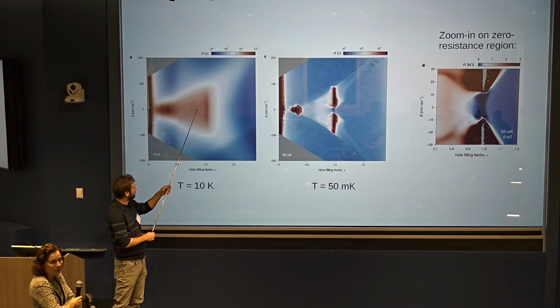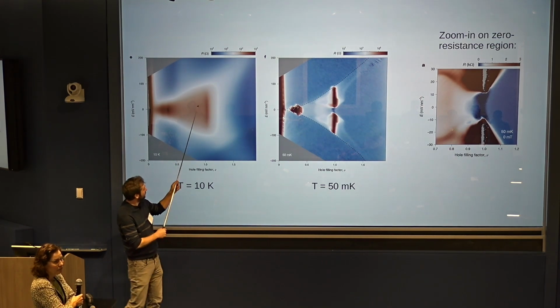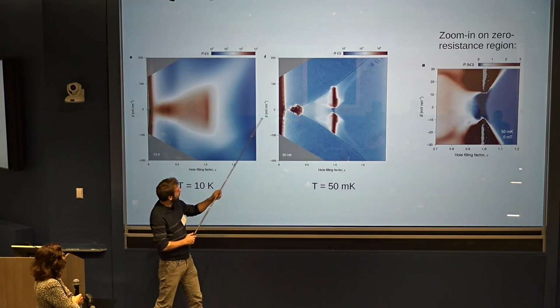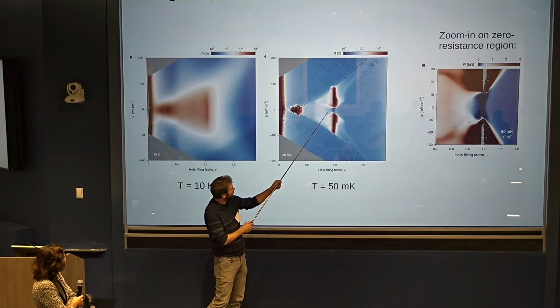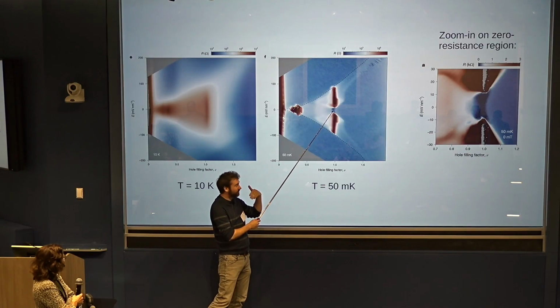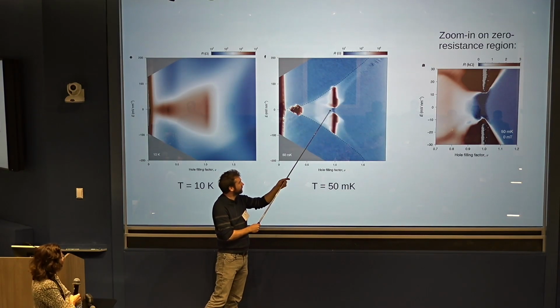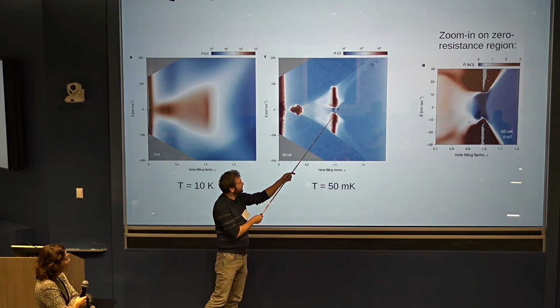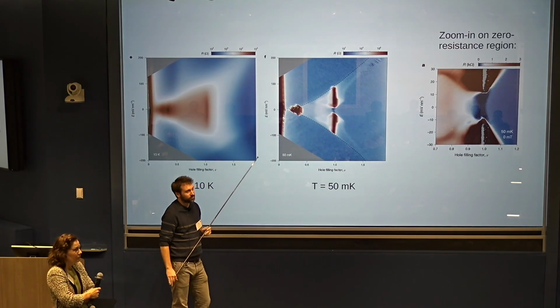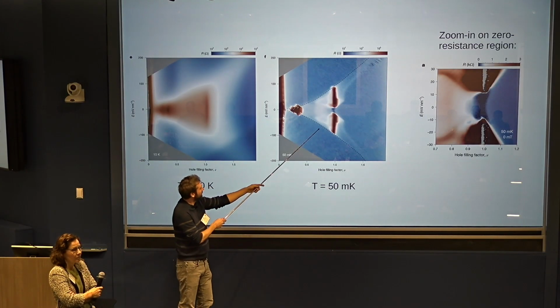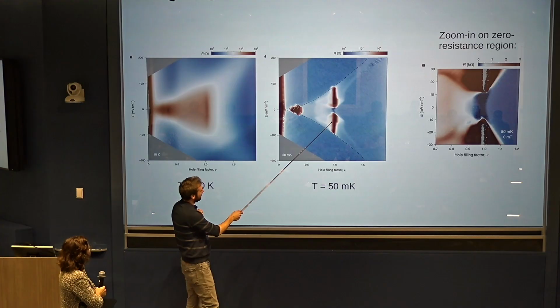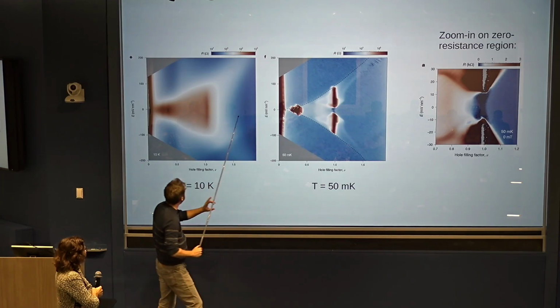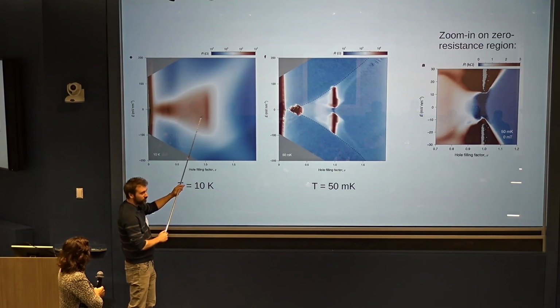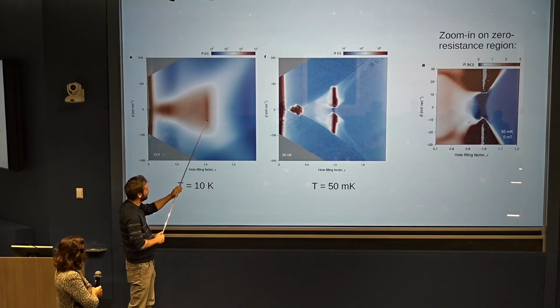And then that could serve as a parent state as you then cool it down, instead of really having these modes condense and form static order, which is actually preempted by superconductivity. And it's exactly in this region where we have these low energy spin fluctuations. But you see, as you heat it up, I think this is a strong piece of evidence. As you heat up the system, this becomes basically a featureless blob, which seems to be just nothing going on here and there. So, yeah.